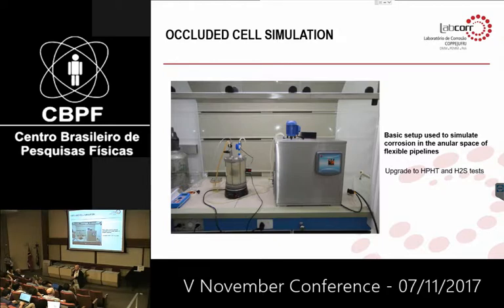So this is a challenge, because it will depend on a lot of input data, and there is a misfit between the different methodologies. The methodology used to emulate the annulus environment has a kinetic. Arno maybe can make a comment, but you did some tests for 1 year maybe, okay? So, and the mechanical tests and corrosion tests are very, very short. So what we need is a stable environment in order to simulate the localized corrosion resistance and the environmentally assisted cracking resistance. So this is what we should try to do for the next years.